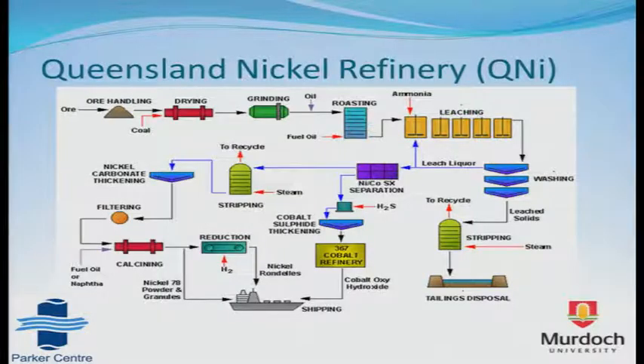So here's a flow sheet of the refinery in Yabulu. The two main parts of the process are the roasting of the ground ore, in which the laterites are basically roasted under reducing conditions. And this is followed by ammoniacal leach, initially under oxygen-free conditions in the first of the larger tanks, followed by leaching which is carried out in aerated conditions in the following 4 tanks. So this is the part of the process that I'm interested in, looking at what problems may be limiting the efficiency of the process.